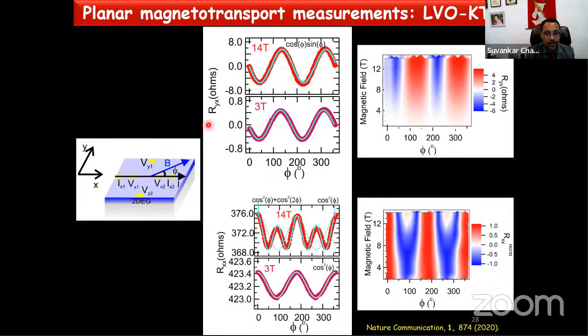So this is the data, rho xy or rho yx, that is, in the planar Hall geometry. What we are doing is that you keep the magnetic field constant and you change the direction between current and applied magnetic field, and this is the change in Hall resistance. And you can see that in any field up to 14 Tesla, it has a twofold signature, which is fitted by cos phi sin phi dependence. And this is the contour plot of this in phi and magnetic field space, and the z direction is the resistance. And you can see that the twofold oscillation continues even up to 14 Tesla field.